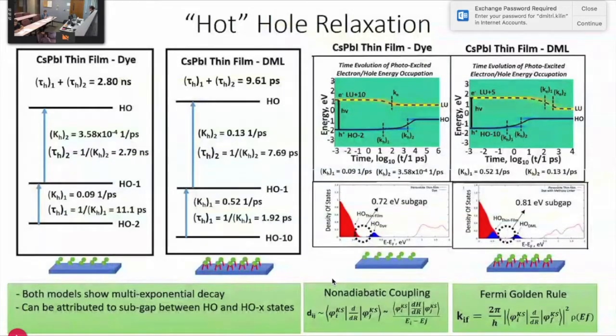And we see that for both of them there is a multi-exponential decay, where for the dye system, it decays from HOMO -2 to HOMO -1, then from HOMO -1 to HOMO. And then for the thin film DML system, it decays from HOMO -10 to HOMO -1, and then from HOMO -1 to HOMO, with two different rate constants. So we can explain why there's multi-exponential decay in both these systems due to the energy gap, as shown in the density of states.